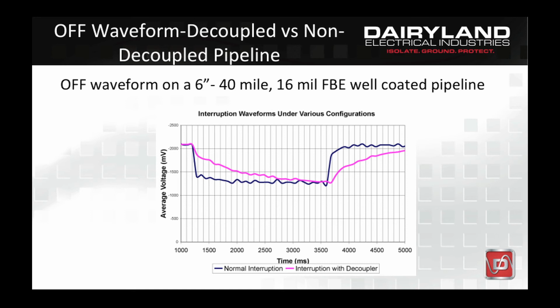On this pipeline, with the on and off cycle time shown, one cannot obtain an accurate off potential measurement with all decouplers installed because the off voltage has not stabilized even after 2.4 seconds. However, in this case, if the off time had been increased to whatever time it took for the voltage to stabilize and a potential measurement were taken and found to be at least minus 0.85 volts, the pipeline would be adequately protected even if depolarization were occurring at that time.